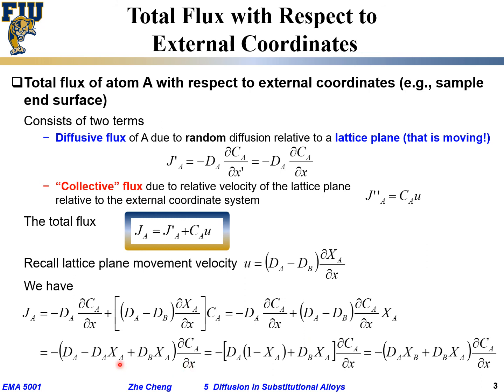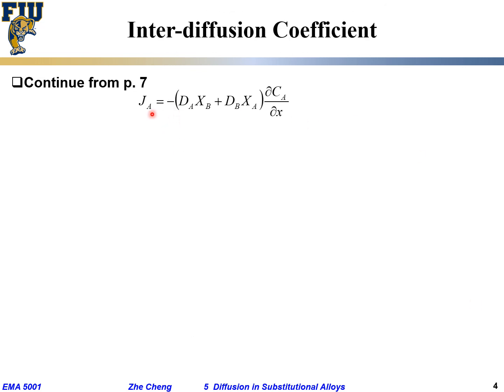And then let's combine this term and this term. dA, we put it in the front. 1 minus Xa, that gives us what? Xb. And the second term, dBxa, we keep. So that's what we are going to have. The net flux of A is minus dAxB plus dBxa times this so-called concentration gradient. So the flux has this kind of interesting crossing term: dAxB plus dBxa times the concentration gradient.